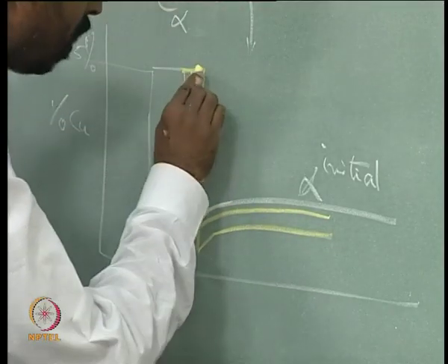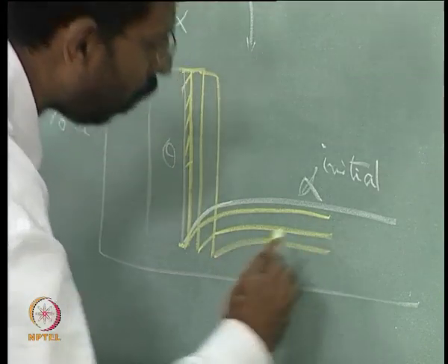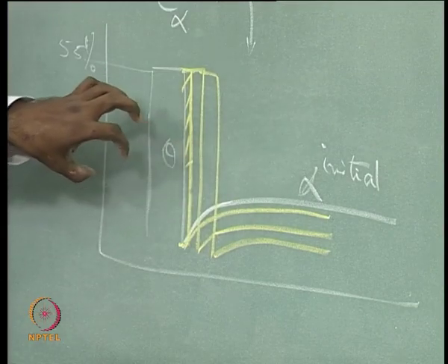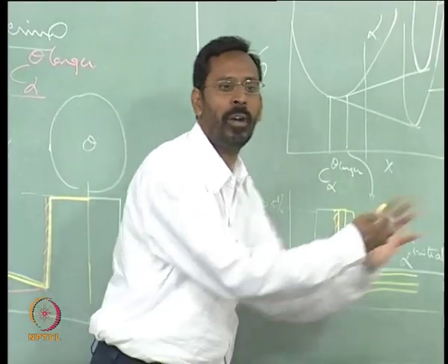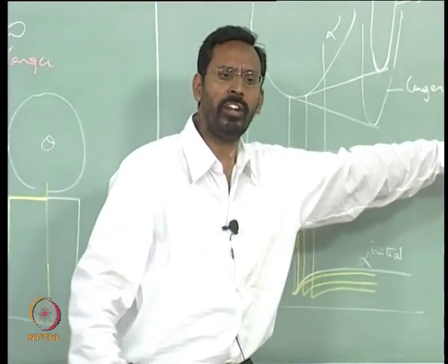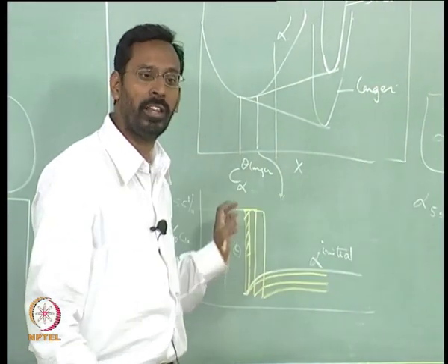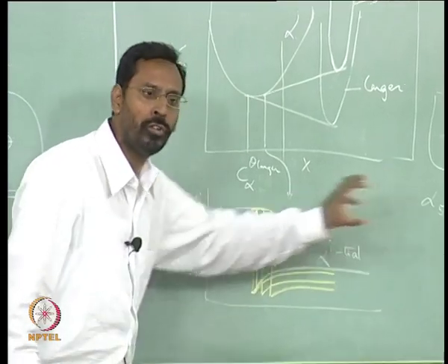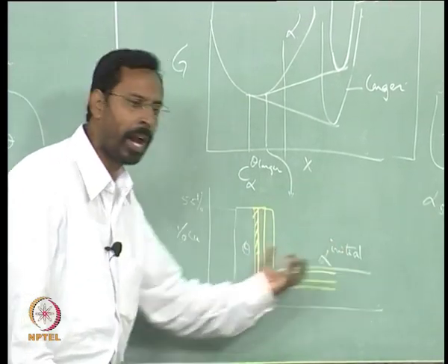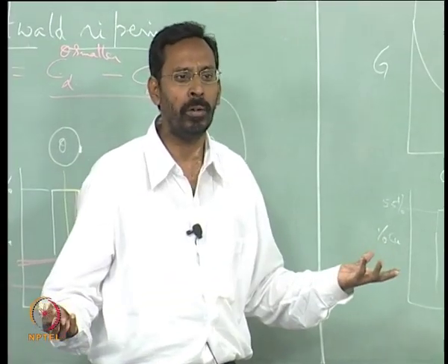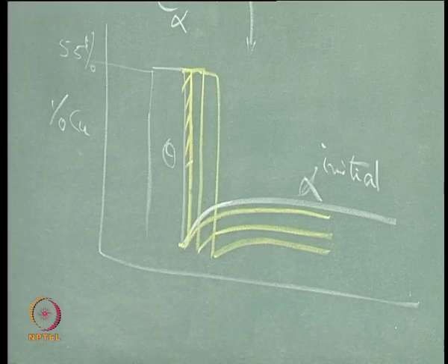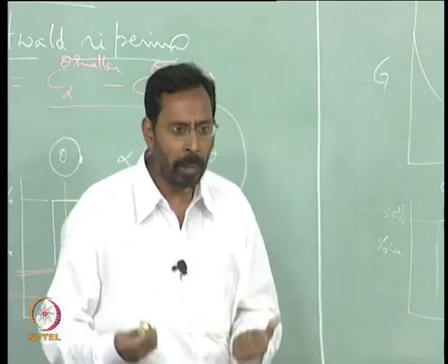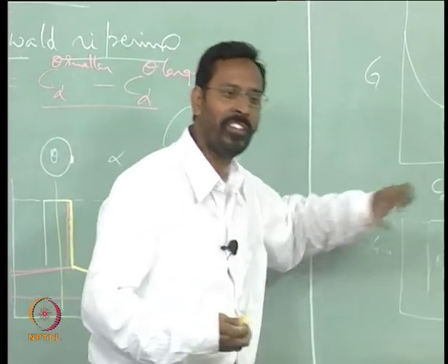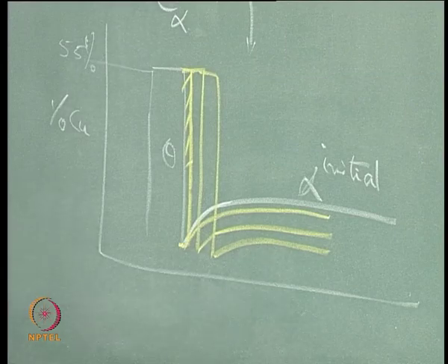Sir, when theta starts growing, does further nucleation still take place? Yeah, I am not talking about that situation, we are talking of one particular theta with respect to its alpha. How does this grow? There will be another nucleation somewhere else, at that region also a similar thing will happen. As this theta wants to grow, the theta can grow only when copper atoms come and join the theta, otherwise theta cannot grow, because theta needs 55% of copper atoms. So, unless they are supplied to the alpha-theta interface, the theta cannot grow.